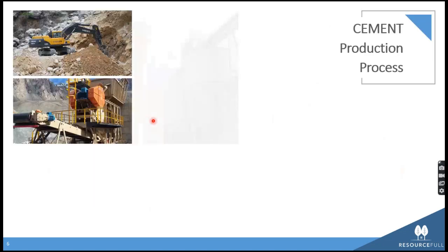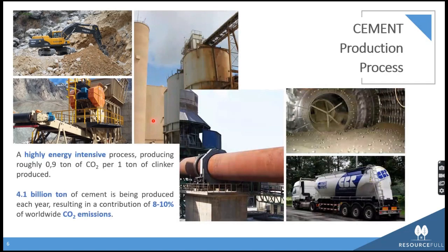And the cement has a high footprint. Maybe you know some of this already, because we start with limestone, calcium carbonate. It's a calcium and a carbonate molecule bonded together. We put that in a big furnace together with some car tires and coal and whatever to produce clinker, the active mineral in the cement. And like that, we produce 900 kilos of CO2 per ton of clinker. Is that a lot? In fact, no.